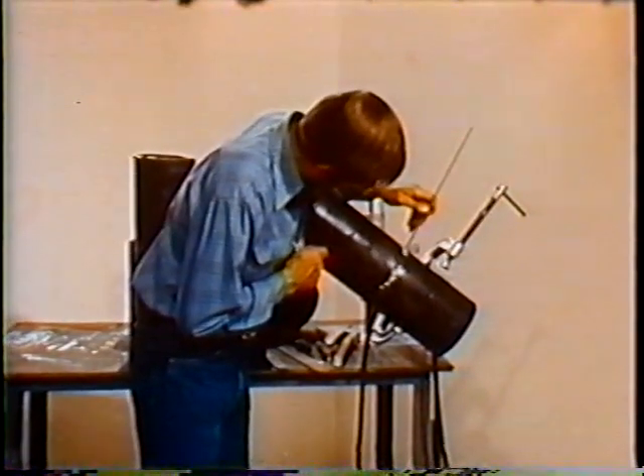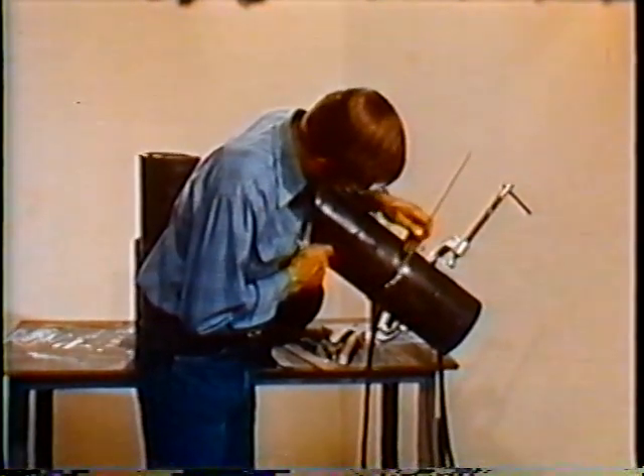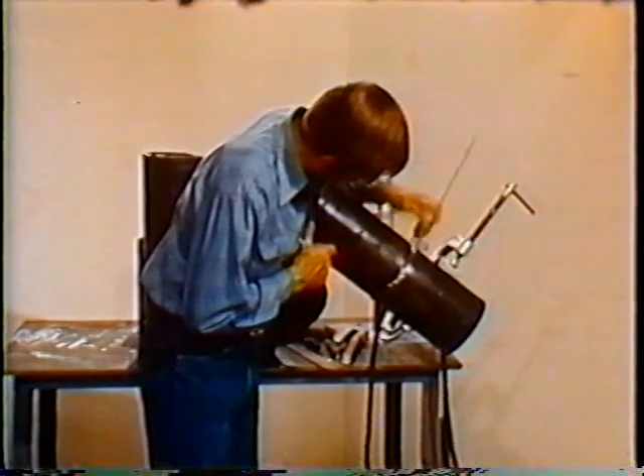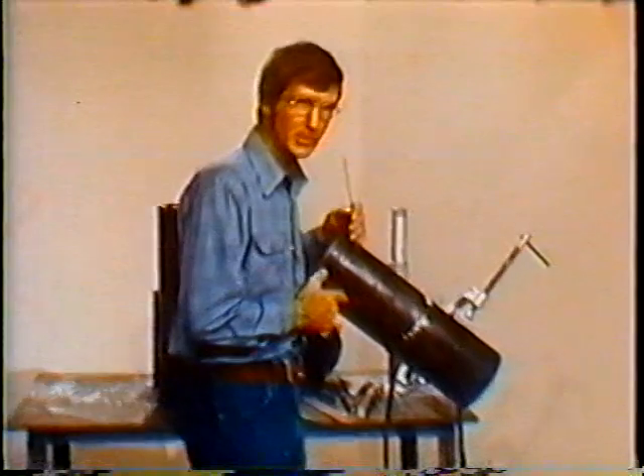And again, fusing into the previous bead that's laying aside of it, leaving ourselves enough room over here to place the third and final pass as you see here. So we'll use 3 beads across the face to cap this weld off. And you'll notice the configuration we have here, about a 1/16 of an inch crown. So you'll notice we're actually using 1, 2, 3, 4, 5, 6, 7 stringer beads around this pipe on Schedule 80 to complete the joint.